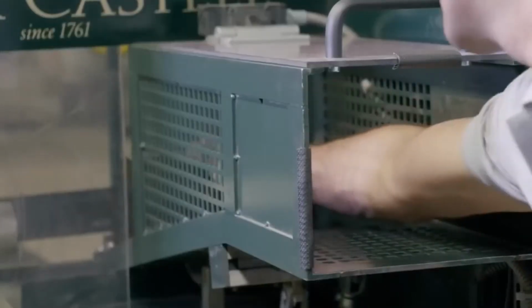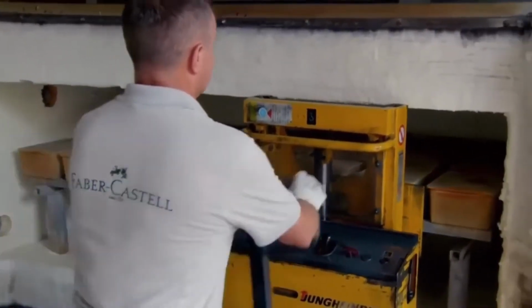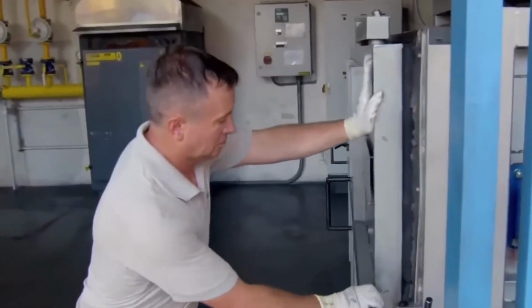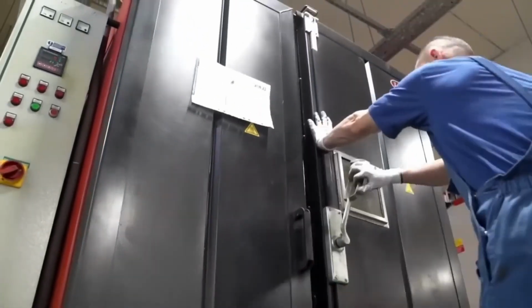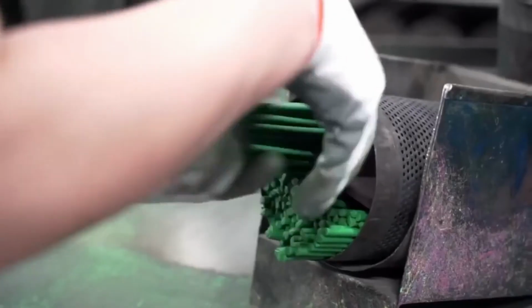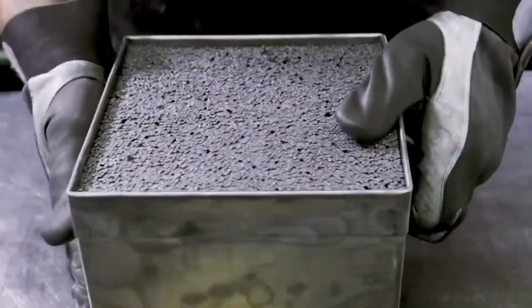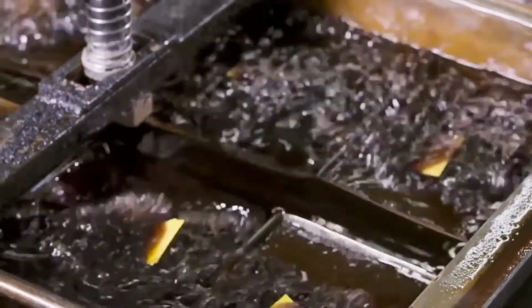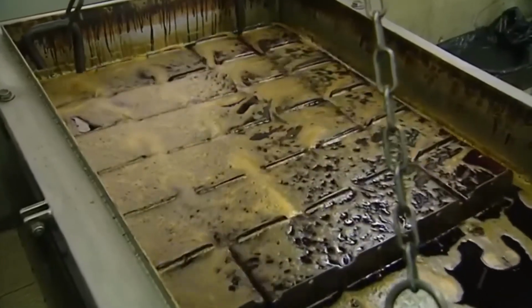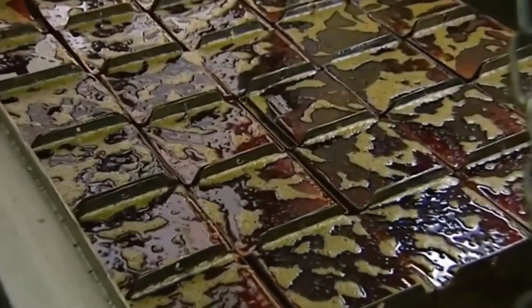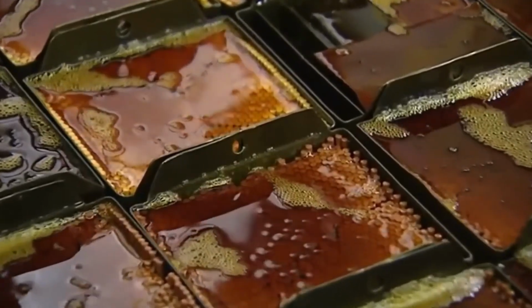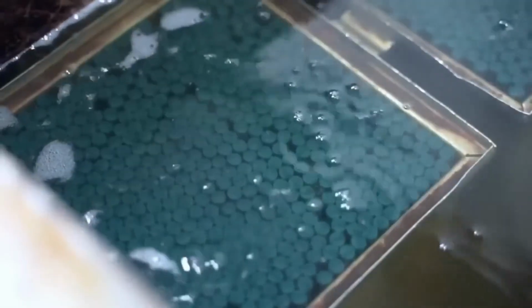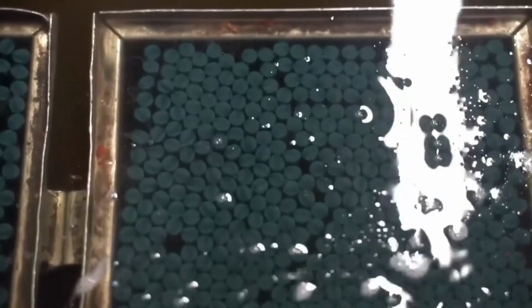However, at this stage, the rods are still soft and flexible. To harden them, they are dried at 120 degrees Celsius for 3 hours before being baked at approximately 1000 degrees Celsius for 45 minutes. This firing process strengthens the lead, making it durable for writing and drawing. Additionally, the leads are dipped into a wax and oil bath to create a smooth texture, allowing the pencil to glide effortlessly on paper.